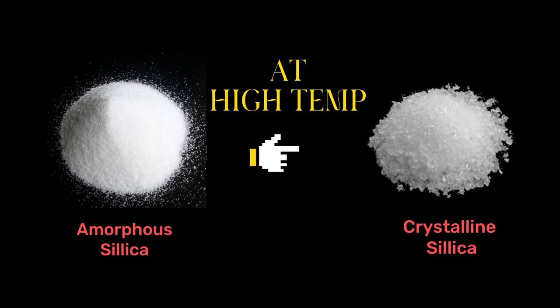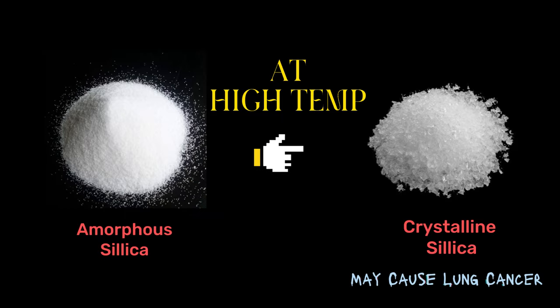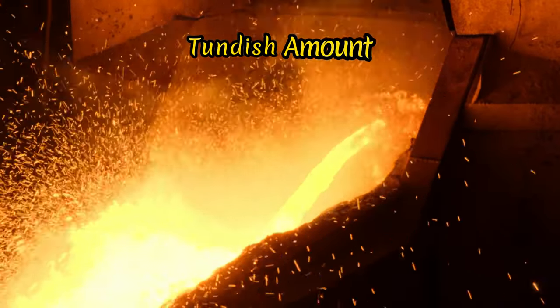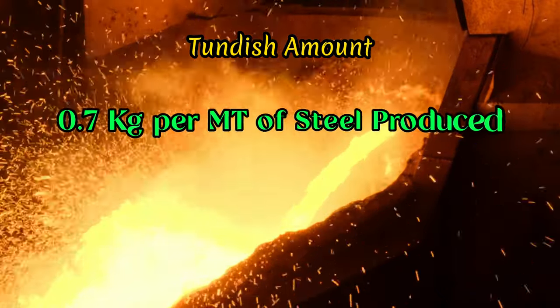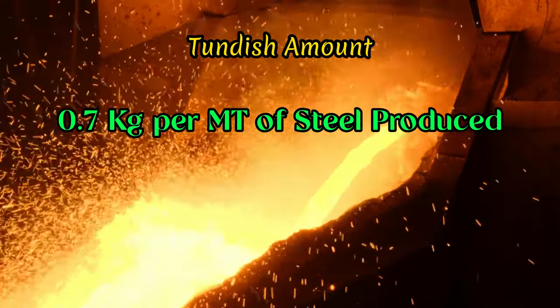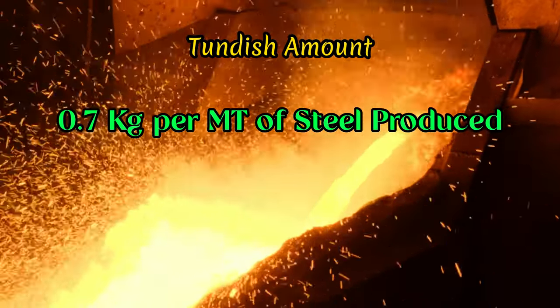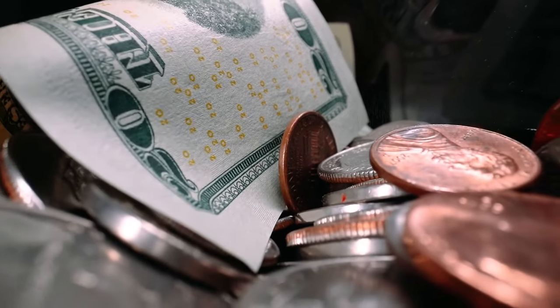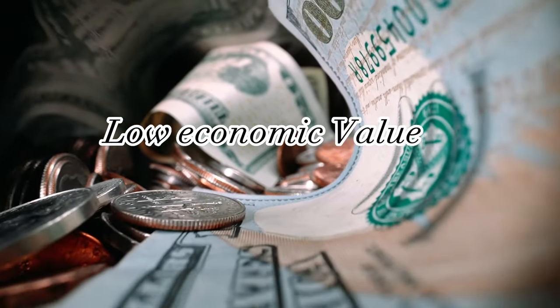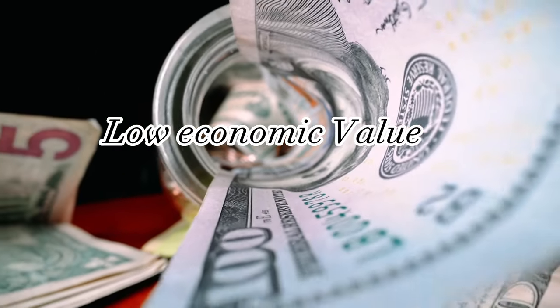But at this higher temperature, amorphous silica changes into crystalline, which can also cause lung cancer. The amount of tundish powder used in steel production ranges between 0.5 to 0.7 kilograms per metric ton of steel produced, but even though it is widely used, the economic value of rice husk ash for this purpose is very low.